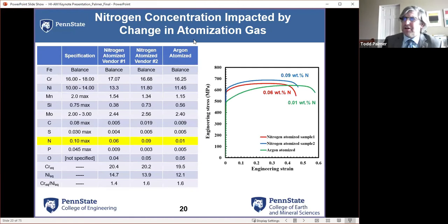So we looked at the nitrogen concentrations, and if you've done any welding of 316 or really thought about austenitic stainless steels, you start looking at these and you're like, yep, chrome looks good, nickel, manganese looks good, silicon, molybdenum is there, definitely L's with the low carbons, sulfur's decent. Oh, we see a big difference in the nitrogen levels. And really, as a welder coming out with stainless steels, that's usually a big red flag that something is going to be different.